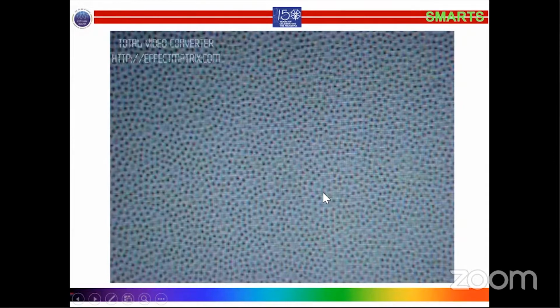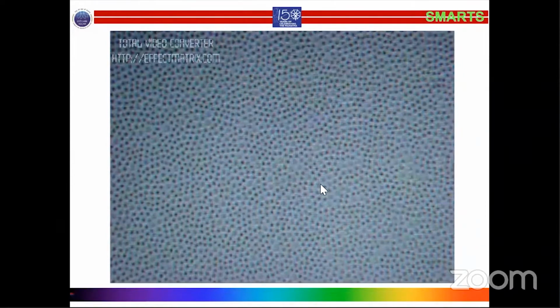The second fluid, which is showing color and is slightly bigger in size, we make using oil globules. Inside the oil globules, we put 10 nanometer size particles, a lot of these particles. These particles are magnetically polarizable, and the particle size is so small that the thermal energy is sufficient to keep these particles suspended in the liquid.